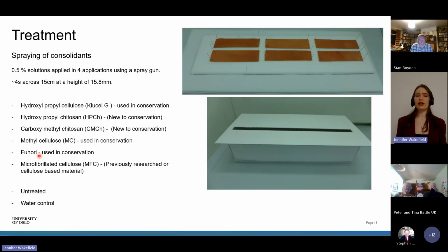So we were looking at these water-soluble modified chitosans, which we'd previously ruled out for the Saving Oseberg project because we were predominantly looking for something that was organic soluble, and this didn't fit the bill. But for the wool, we were looking for something water soluble, so we decided to have a go with these as well. And the chitosan has a similar structure to cellulose that's found in wood, but it has an amine group, and that amine group can attach to metal ions, so it could prevent some problems coming from the metal ions and the migration of the metal ions.